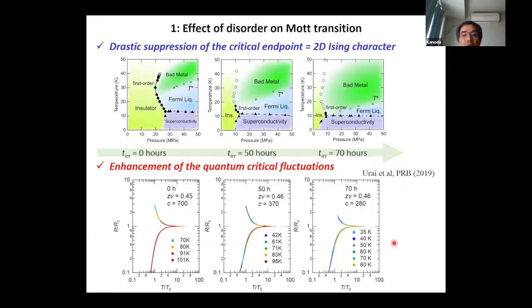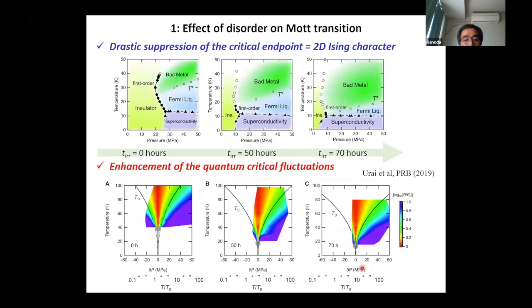And with such a very weak disorder, we still observed a very good scaling. The exponent is nearly the same for all the cases: the pristine crystal, 50-hour irradiation and 70-hour irradiation, and the critical endpoint is decreasing. However, the similar scaling holds. But the quantum critical region goes down with increasing disorder.